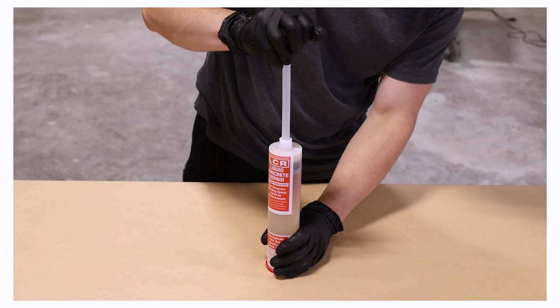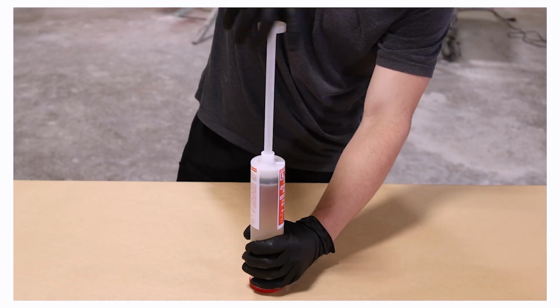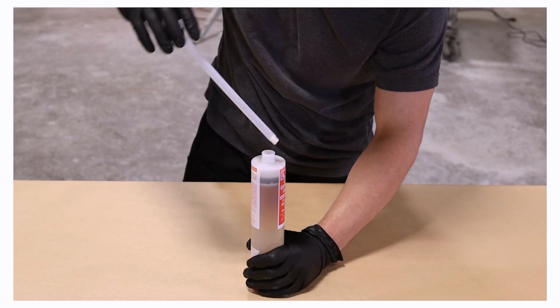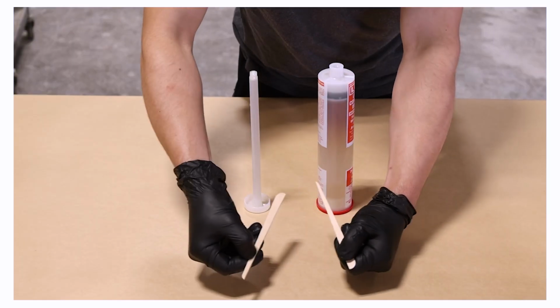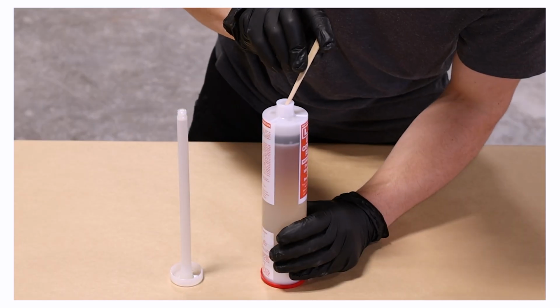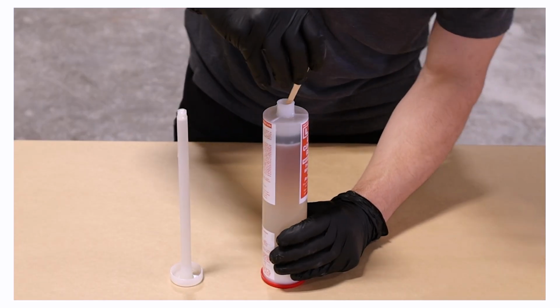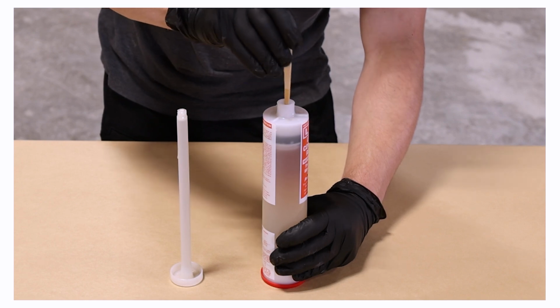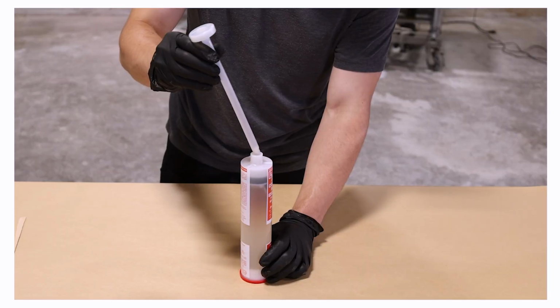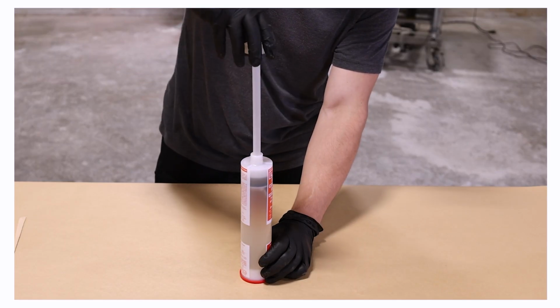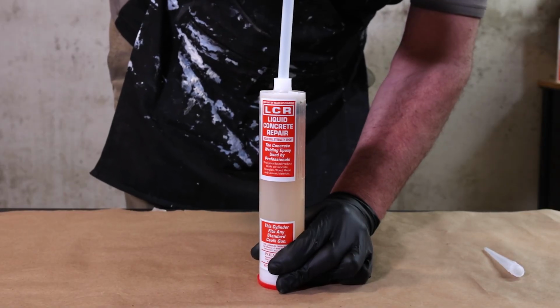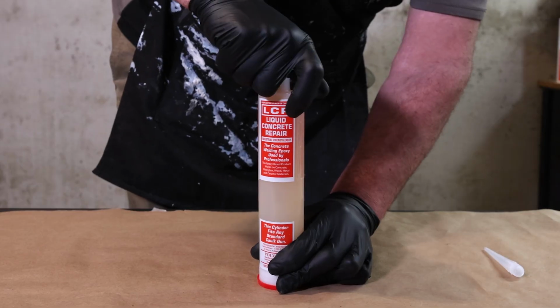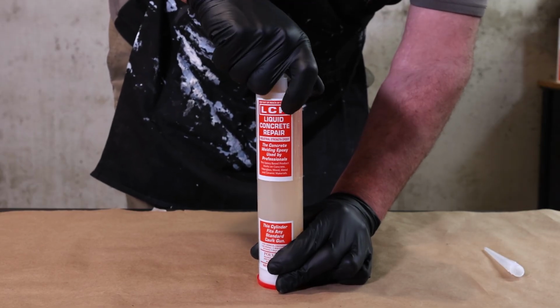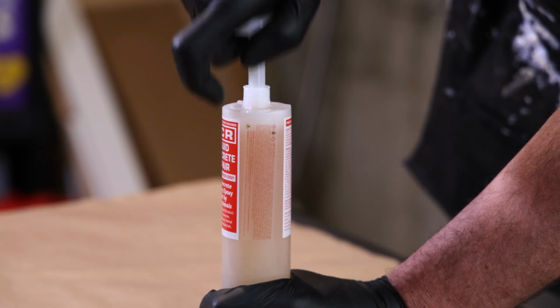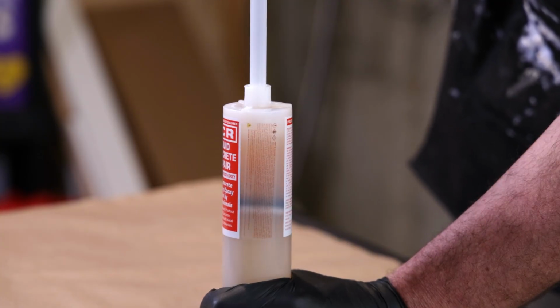If the foil doesn't break, the plunger may become difficult to move. If this happens, remove the plunger and carefully puncture the foil through the top of the cartridge using a wooden skewer or something similar. This ensures the resin mixes properly and helps prevent any leakage from the bottom. Once the foil is punctured, reattach the plunger and continue with the next step. Now, in order to mix the resin, pump the plunger with 20 to 30 full strokes until the resin reaches a uniform color. The resin has a working time of about 30 minutes once mixed.